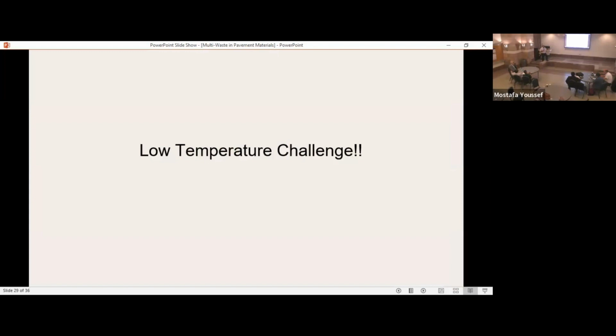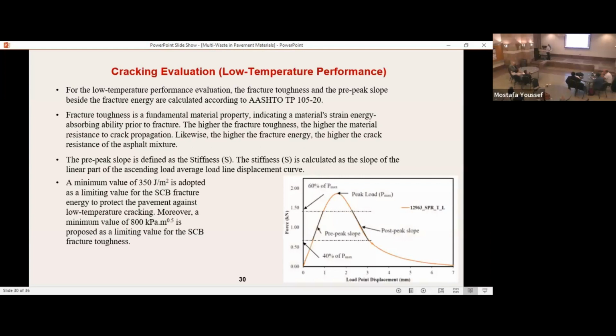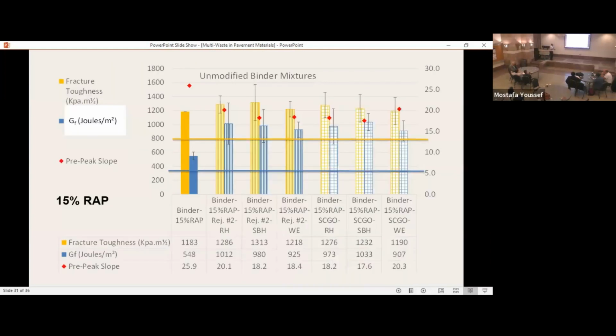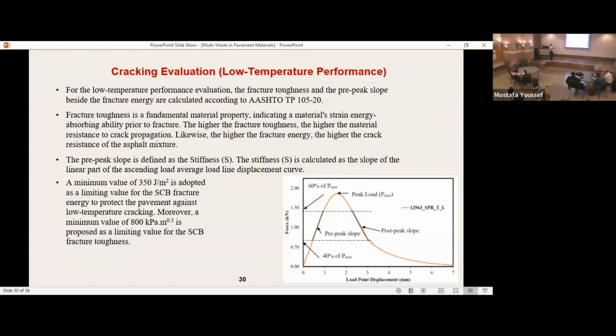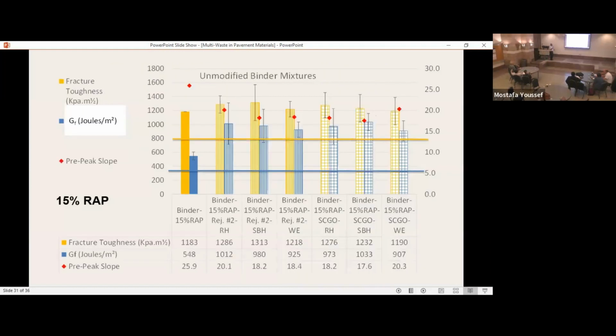And what would really seal the deal for us is working with low temperature. At low temperature, asphalt naturally, even unaged, becomes very brittle. So we did a test on something similar to the previous test. Again, a controlled crack, a notch to initiate the crack, and evaluate the fracture toughness, fracture energy, and the slope of crack opening.